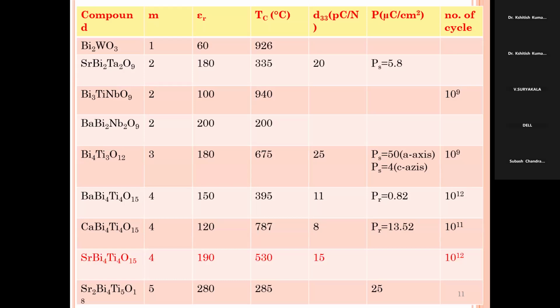In this table, on the left side I have written the compound name, and M is the number of layers, 1, 2, 3, 4, 5. The next one is the dielectric constant, and the next one is the transition temperature. D33 is the piezoelectric constant, P is the polarization, and the number of cycles is also written. If we compare this table across the 1, 2, 3, 4 and 5 layer, we got strontium bismuth titanate, the red one here, and this is the 4 layer structure.